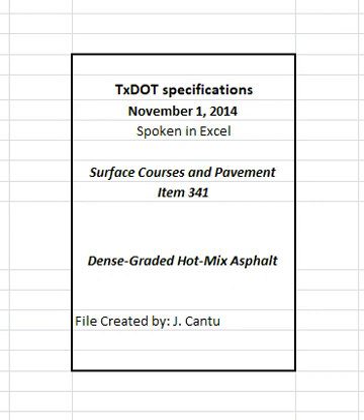Control the mixing time and temperature so that substantially all moisture is removed from the mixture before discharging from the plant. Determine the moisture content, if requested, by oven drying in accordance with TEX 212F, Part 2, and verify that the mixture contains no more than 0.2% of moisture by weight. Obtain the sample immediately after discharging the mixture into the truck, and perform the test promptly.